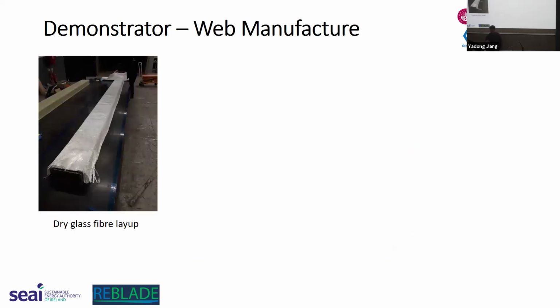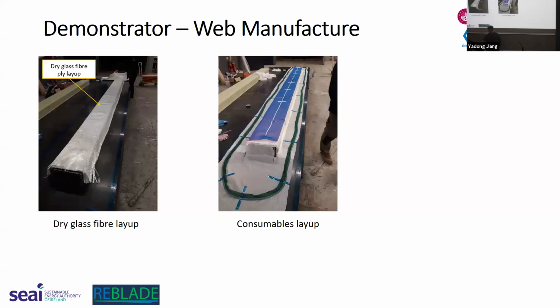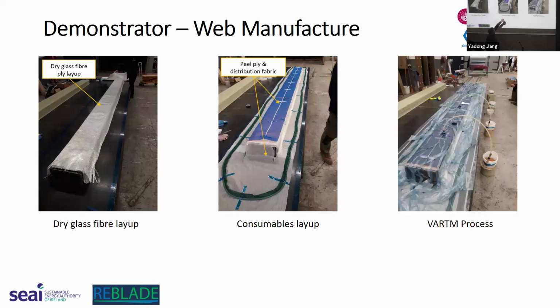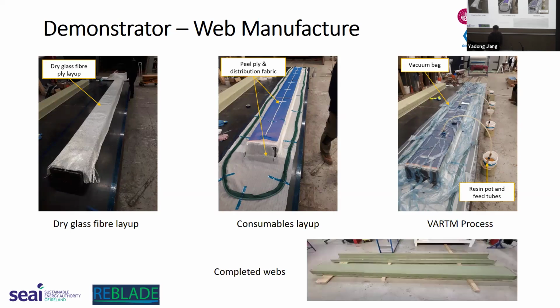Then the demonstrator web manufacture. So we started off with laying up the dry glass fiber. Then we laid down the consumables, which are a peel ply and distribution mesh in white and blue. And then we have the vacuum bag and the resin pot and feed tube. So that's where the resin will be sucked into the component, and it'll wet out and go towards the vacuum pump. And then these are the completed webs once they're demolded, trimmed, and dimensionally inspected.